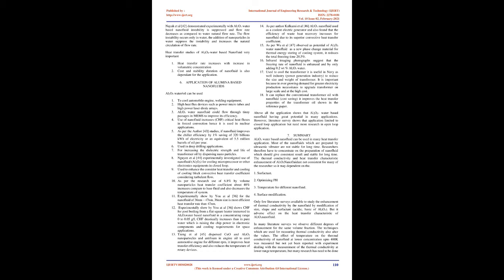Bang et al. 37 studied boiling heat transfer characteristics and pool boiling heat transfer phenomenon for Al2O3 water nanofluids and compared results with pure water. The author shows poor heat transfer performance of nanofluid in boiling heat transfer due to the deposition of nanoparticles on the surface of the plate, both in horizontal and vertical pool boiling. Surface characteristics change due to the deposition of nanoparticles, hence CHF has increased.